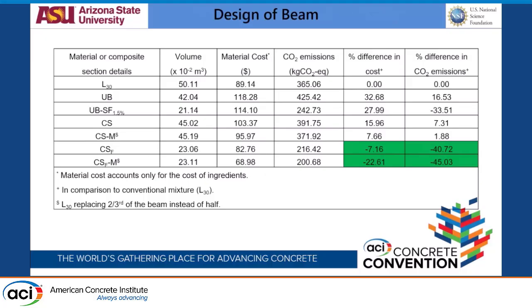Now, how does this correlate to when you actually have to design? To show that, we designed a 6-meter long beam to carry a 3 kilonewton per meter UDL load. Keeping the width constant at 200 mm, we are just varying the depth to see what depth is required to carry that load. Based on that cross section, we calculate the volume, and then we correlate that volume to how much material cost we have for the section and how much carbon dioxide we have because of that section. And how does that correlate from the homogeneous beam to the composite beam?